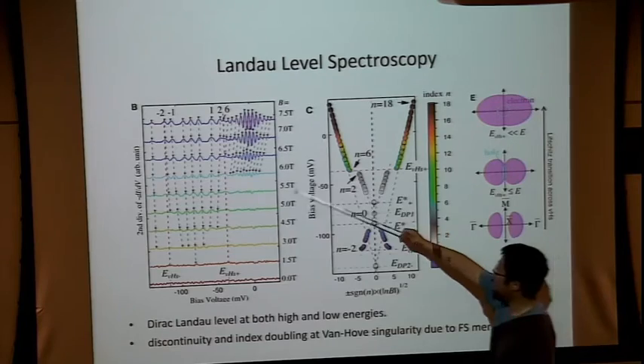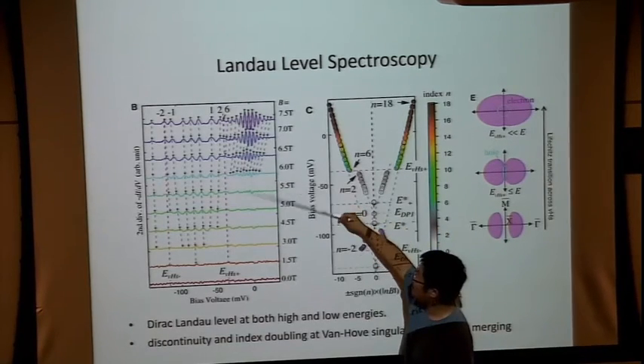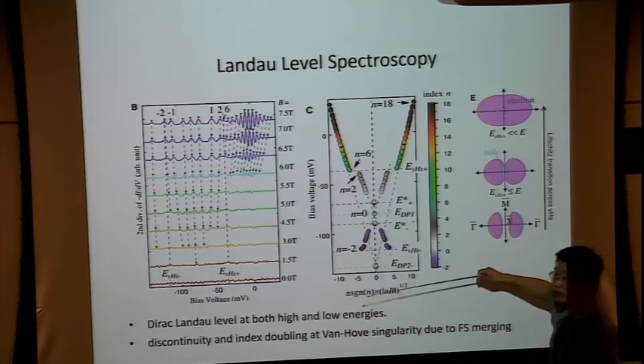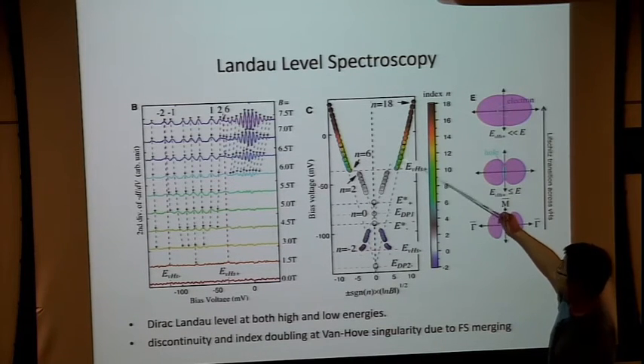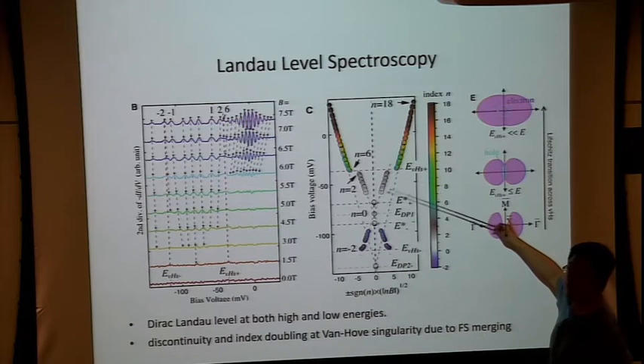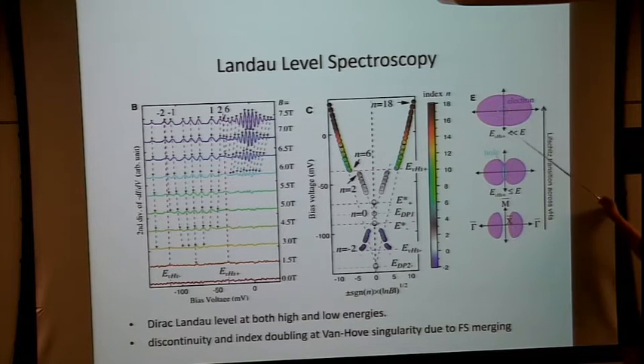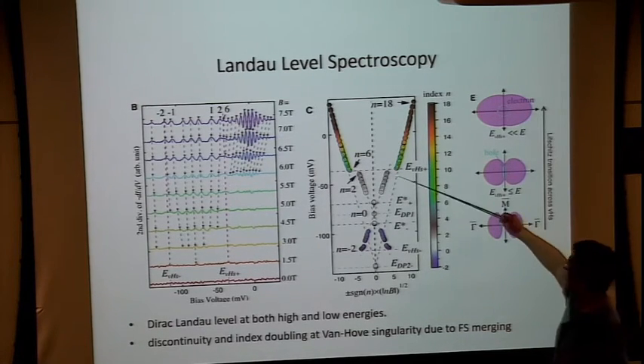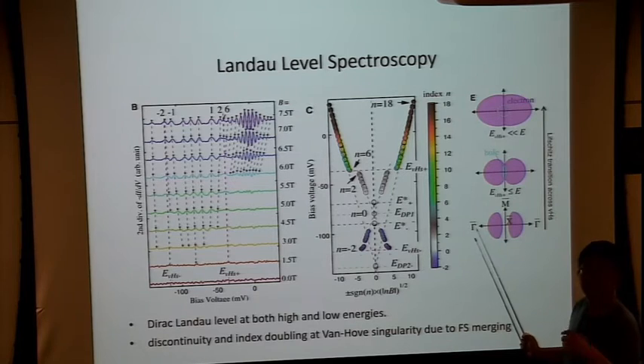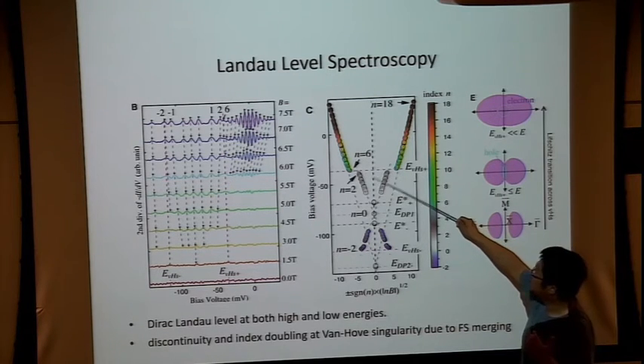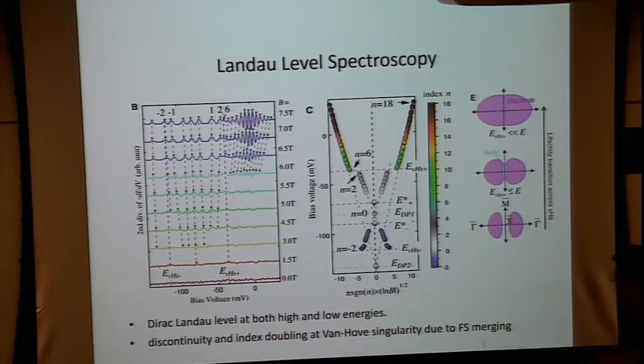So there's a lot of features in understanding how the Landau levels depend on the magnetic field. I won't go into the details. For example, you see that the Landau level index jumps at a particular energy, which corresponds to the Van Hove singularity you see at zero magnetic field. And this is precisely because above and below that critical energy, we have a change in the topology of the Fermi surface, with two disconnected Dirac pockets at low energy. It evolves into a big pocket at high energy. So that's why at this transition critical energy, the size of the Fermi surface for cyclotron orbits doubles. So that's why the Landau level index changed from 3 to 6. There's a discontinuity here.